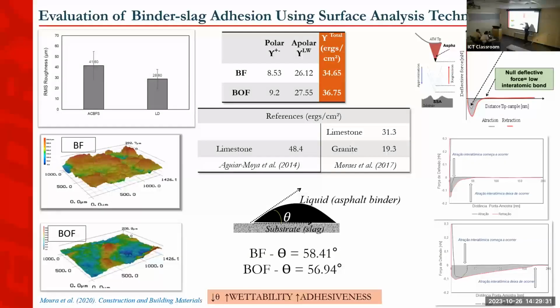Let's check the surface free energy results. Total surface free energy: what my student and I were expecting was that the BOF could have a much higher surface free energy, which could justify why BOF was better. But again, the values were similar, and still comparable with limestone aggregates, which are the ones that adhere better to the binder, compared to granite aggregates.